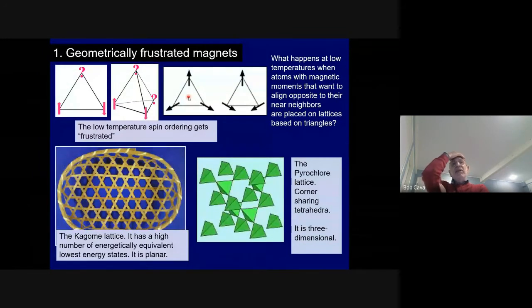And when you do that, there's a larger number of degenerate states possible. So you end up with many possible low energy states, which results in, let's say, magnetic frustration. So we can tell how frustrating a lattice type is by looking at the ratio of the Curie-Weiss theta, which is a measure of the average interaction energy between these spins, and the actual ordering temperature.